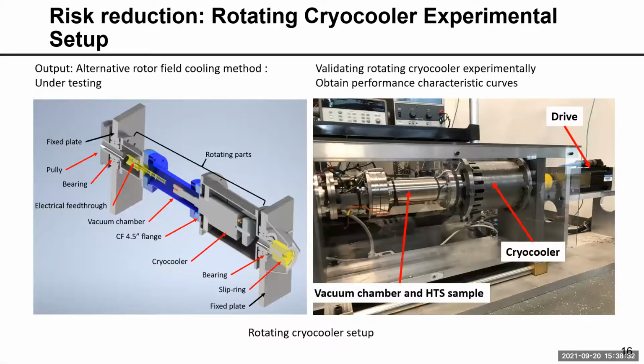So this is the other experiment we are doing here at University of Illinois. Here we are looking at whether we can cool the rotor windings on the rotor without sending the hydrogen through the transfer coupling. You can see that the cryocooler is located in this part, and we have a vacuum chamber here, where we put the HTS sample, and the whole system is rotated by the drive.